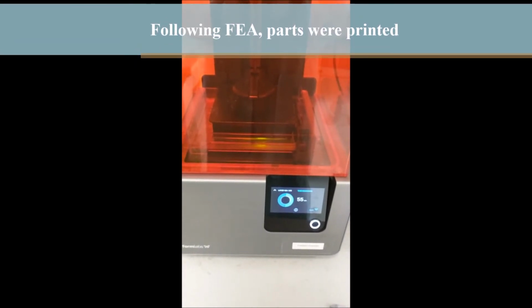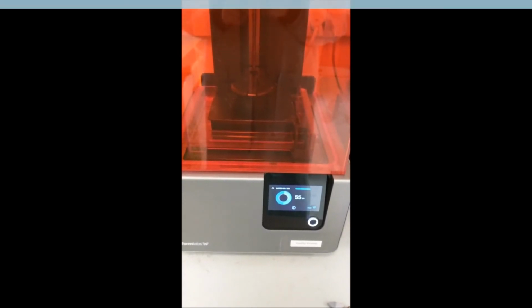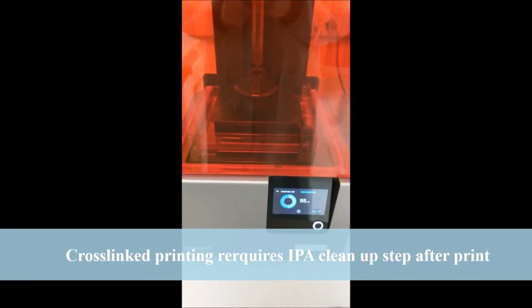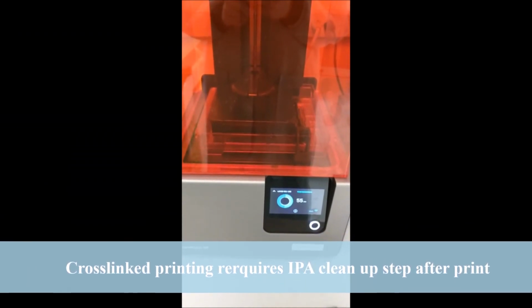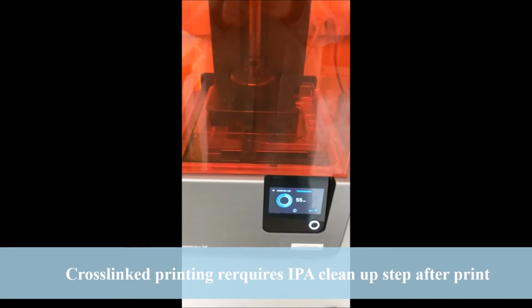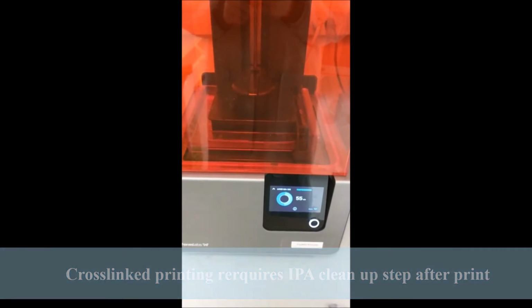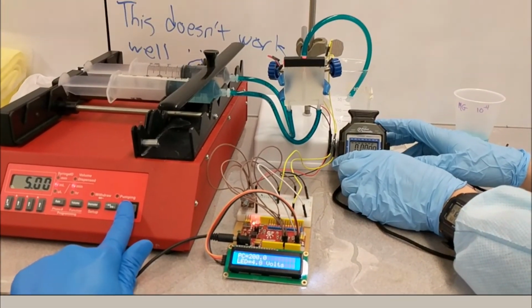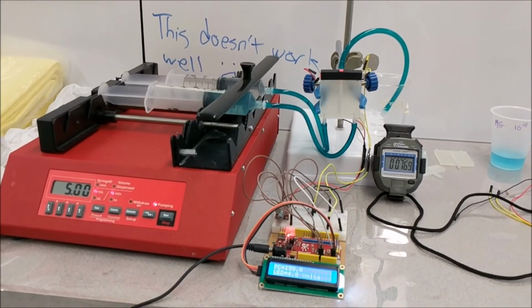They were printed with cross-linked epoxy, and the finished product was soaked in IPA. IPA was later pushed through the reactor to remove any uncross-linked material and to ensure there were no leaks or obstructions. Once the design was printed and ready for use, it was placed in the test stand.